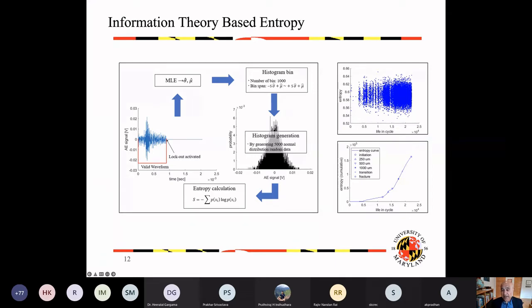So if you look at this on the side, each of these waveforms is transformed into one of these dots in this graph. You can see this is the amount of entropy as the time goes by, as we are adding more and more damage to the component. And if you look at this, you don't see anything. You just see a bunch of dots. You see a little bit darker area here. But if you average them over a certain period of time and find averages, actually you see an increasing entropy. You see the entropy is actually increasing because of this damage. So that tells us the information entropy increases, which then correlates closely with the damage.